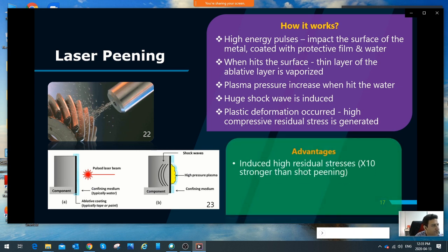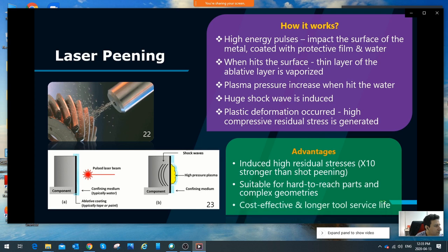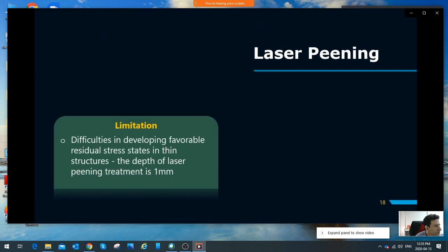The first is it can induce a very high compressive residual stress, which is 10 times better than the conventional shot peening. And the second one is it is very suitable for hard to reach parts and parts with complex geometry. And the last one is it is cost effective and provides longer tool service life. And there is a limitation, which is we are in difficulties in developing a favorable residual stress in thin structures because the depth of the laser peening treatment is about 1 mm.